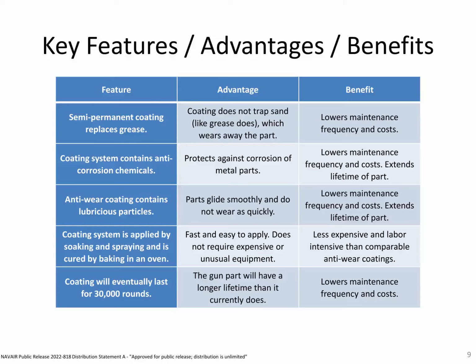The coating system is easy to apply. It can be applied through dip coat, brush plating, or spraying, depending on which part of the coating it is and what the user prefers to do. Because it's a solution-based process, it's fast and easy to apply, and it doesn't require expensive or unusual equipment, especially equipment the Navy depots would not be familiar with. This means it's a less expensive process, it's also less labor intensive, and it can be performed by a minimally trained technician.